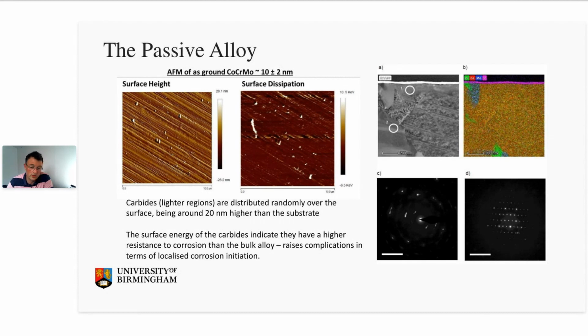which some of our more recent work is now showing are intrinsic to ultimately the debris that's generated from these devices. But what we also see is that we can get segregation within the alloys as well. So we can have segregation in moly and chrome, which is particularly important from a protein interaction, from a selective dissolution point of view. And what we do know is that proteins and phosphates interact differently with these different elements. And some of the work that we published recently has demonstrated that we can get preferential dissolution of these alloys just under simple static conditions.